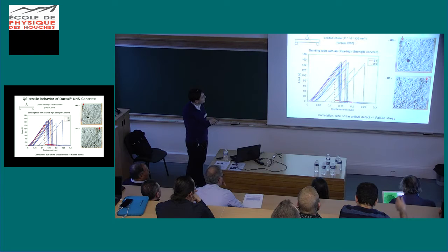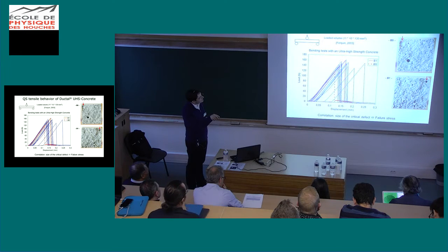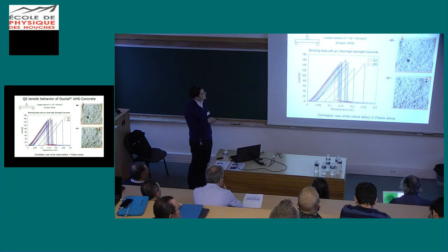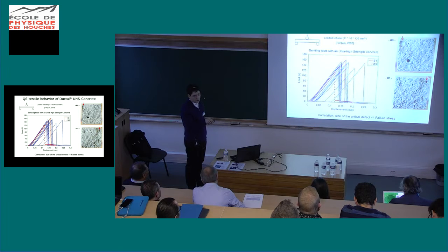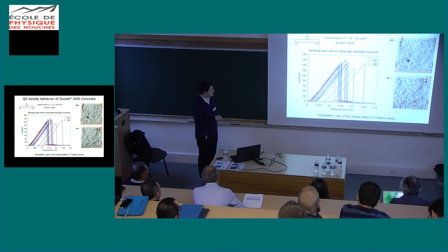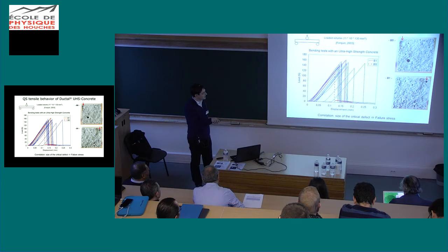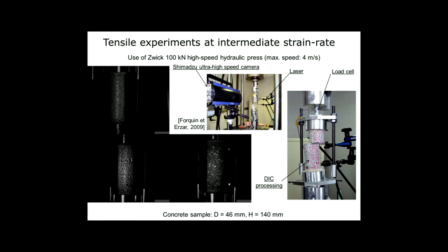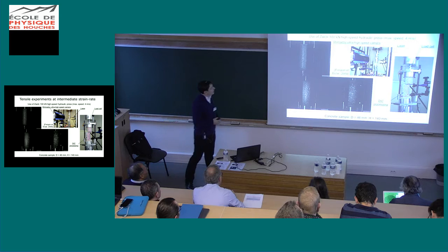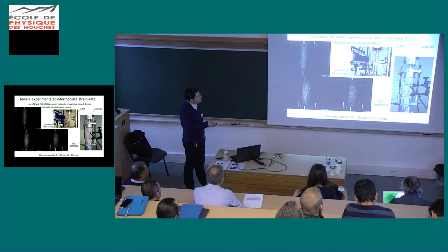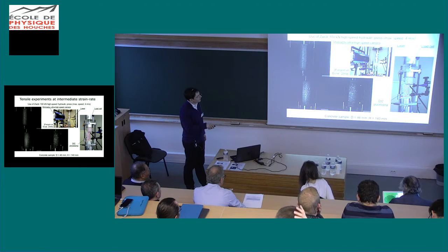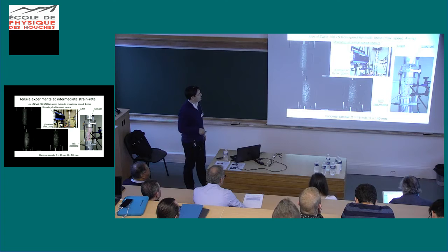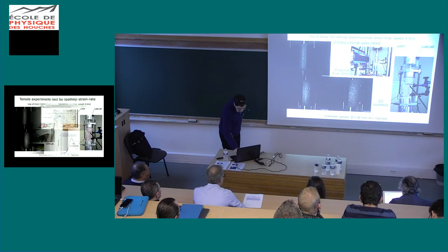And you can see, for instance, the B5 sample, where the tensile surface was here at the top, and you can see the large pore near the tensile surface, whereas in B1, a much smaller pore triggered the failure. Okay, so there is an obvious correlation between the size of critical defects and the corresponding failure stress. Okay, but we can also perform direct tensile tests. It's less convenient because you have to glue the sample, so you can have a triggering of fracture near the sample ends. But okay, I will be fast.